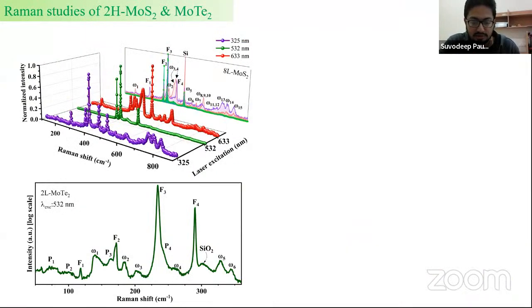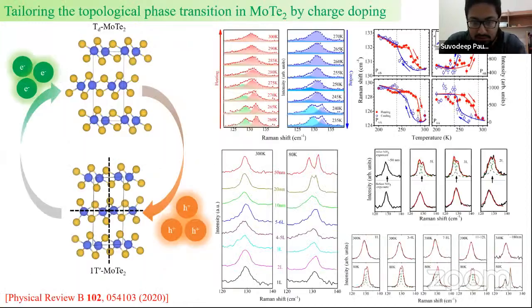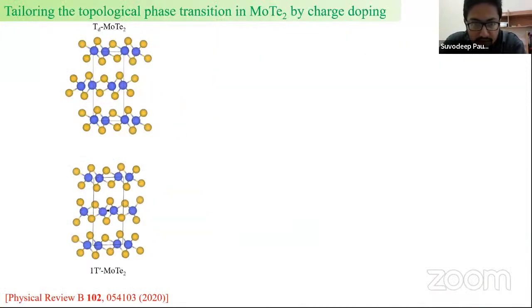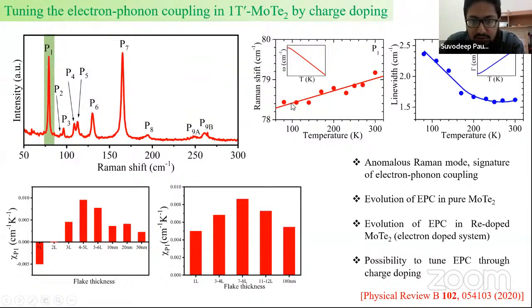If you look at this image, this is where the phase transition takes place. But more or less, we can say that the behavior of the anomaly, which is basically a signature of the electron-phonon coupling, is fairly consistent below and above the phase transition. So it's difficult to comment whether the electron-phonon coupling increases with the change in phase.